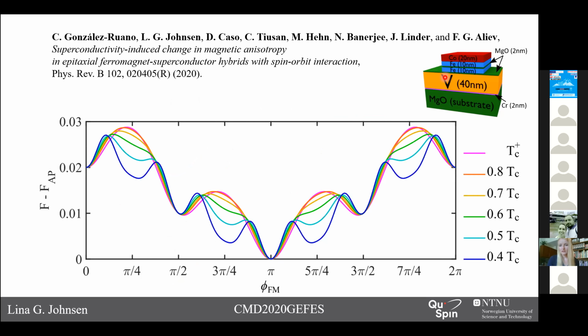Also in this model, in addition to the superconductor and heavy metal ferromagnet layer, we have a magnetically hard layer of iron cobalt. In addition to this change in the free energy we saw before, it prefers anti-parallel alignment of the two magnetizations. What they showed was that if the magnetizations are anti-parallel in the first place, then for a normal metal, if you apply an external field in this direction towards 2 pi, you can force the magnetization to go to this minimum at 3 pi/4 if you're in the normal state.